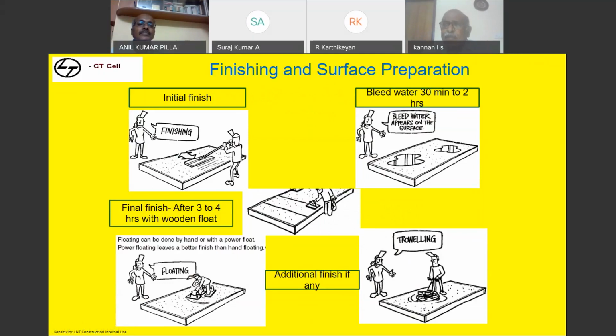When it comes to finishing and surface preparation, do the first finish after compaction. The mason will do the finishing with the float or straight edge and all. After some time, you will find bleed water will come on the surface. Concrete has to bleed. Some amount of bleeding should happen. Bleed water should not flow like a river. Okay. During that process of bleeding, you will find some cracks.